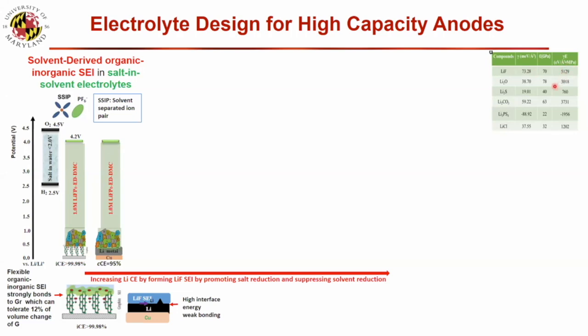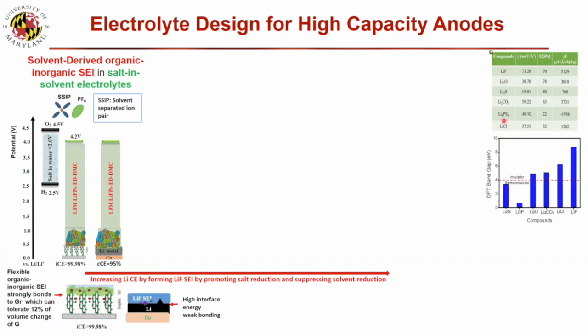Normally, polymer has very strong bonding with the lithium, so in that case, we prefer ceramic. Among all ceramics, we prefer lithium fluoride. And second, lithium fluoride also has the largest band gap. That means electronic conductivity is the lowest.